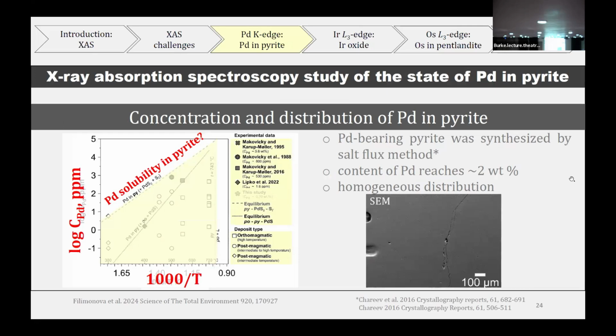The first example I want to show you is the state of palladium in pyrite. We noticed that the concentration of palladium in pyrite is increasing with temperature through a rough assessment of the natural data and synthetic data. We suspected that it might be solubility, but in order to prove it, we need to prove or disprove that it's a solid solution. Because if it's inclusions, we cannot build any kind of thermodynamic model at all. So we synthesized palladium-bearing pyrites. They contained very high concentrations of palladium, up to 2%, and the distribution was quite homogeneous.